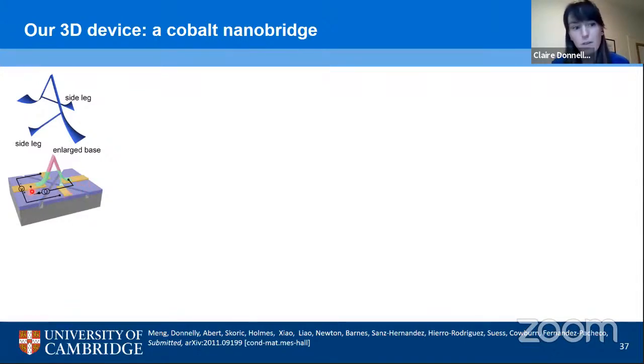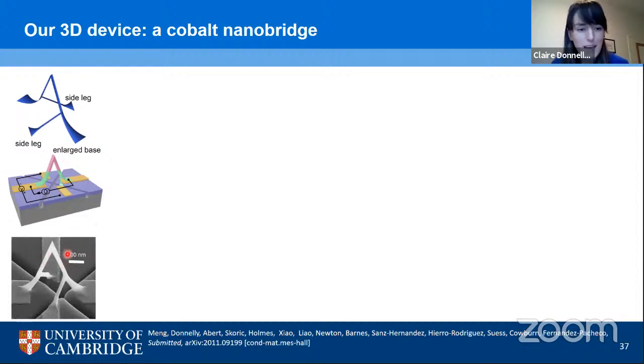Now we can notice a few things about this structure. So first of all, we're really able to bring the magnetic material in a controlled way into the third dimension. This is the first step towards going to 3D. We're also able to design the structure such that we have a relatively efficient, in terms of space, four-point probe measurement system, which allows us to characterize the magnetic properties of this structure. And you can see in this SEM image that we are able to realize the structure with a high degree of accuracy with FEBID.